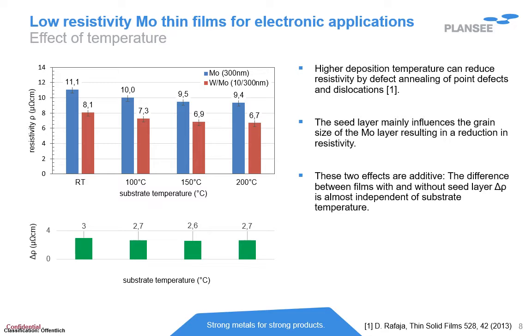can be observed even with increased temperature. So a 30% reduction in resistivity is possible at room temperature. The same effect can be achieved, but at lower absolute values, when you increase the substrate temperature during deposition. On these graphs, you see the influence of different substrate temperatures ranging from room temperature to nearly 200 degrees Celsius. And what you can also see is that the difference in resistivity for all of those different substrate temperatures between a single layer Mo film and the approach using a tungsten seed layer is more or less in the same range. So there is always a gain of about 30% in resistivity possible when you are using the seed layer.